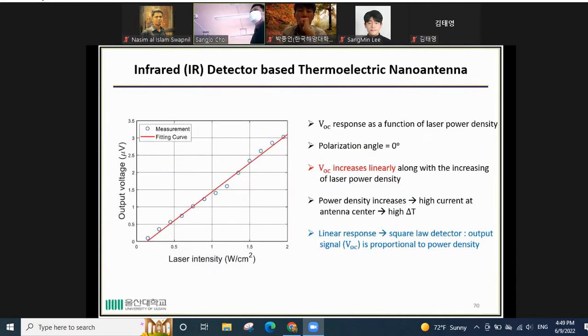And we also perform the measurement of VOC response as a function of the laser power density to demonstrate the infrared detector based on the thermoelectric nano antenna. So we measure with 0 degree polarization angle, and this is the measurement result of the output voltage as a function of the laser power density. So you can see from this plot that as the laser intensity is increased, the VOC increases linearly. So when the power density increases, the high current at the antenna center also increases, so that creates a higher delta T. This shows a linear response, so we can consider our structure like a square law detector, where the output signal is proportional to the power density.